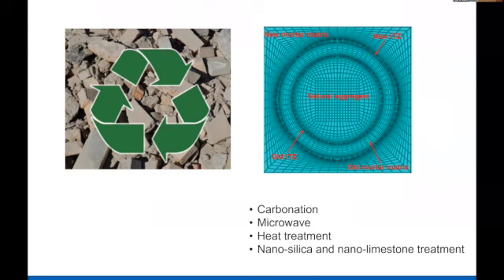But one of the challenges is that if you look at this picture, you have a natural aggregate which is surrounded by, in a recycled aggregate, a thin layer of cement mortar. This is very porous, and that absorbs a lot of water. And this means that workability is a big issue when you use recycled aggregate. So how can we improve it? And people are doing some interesting work.